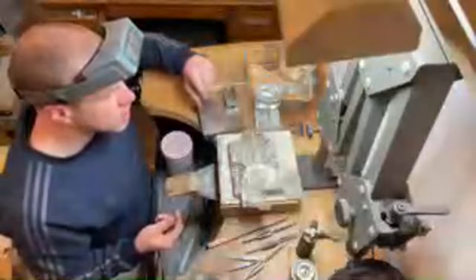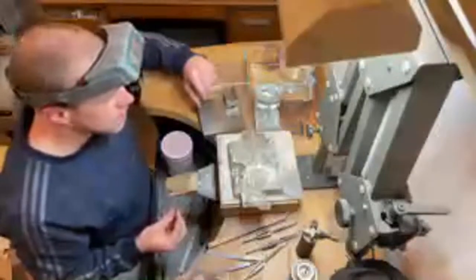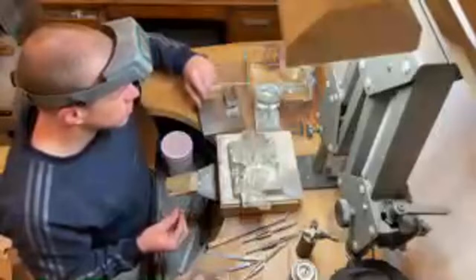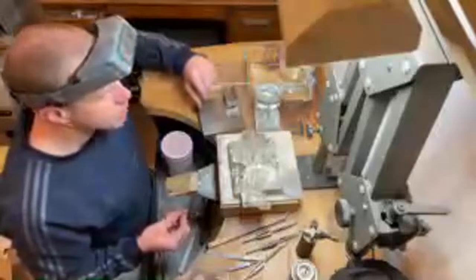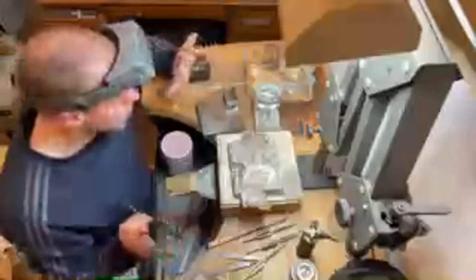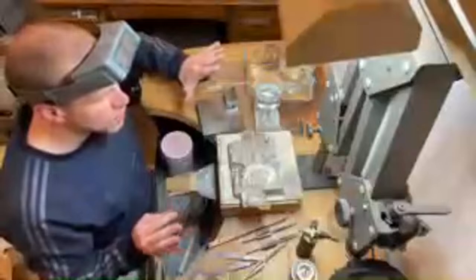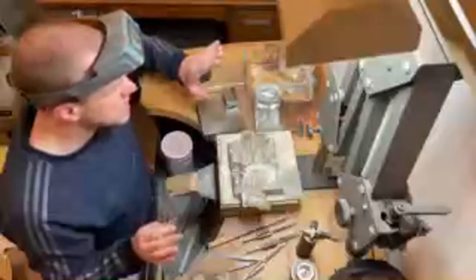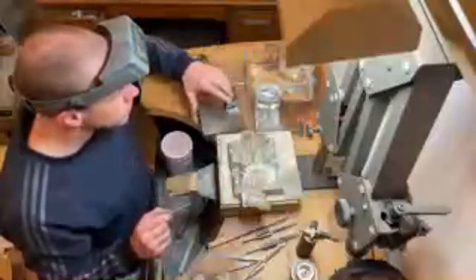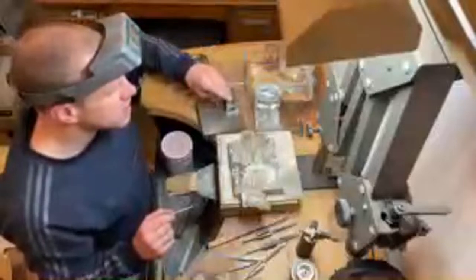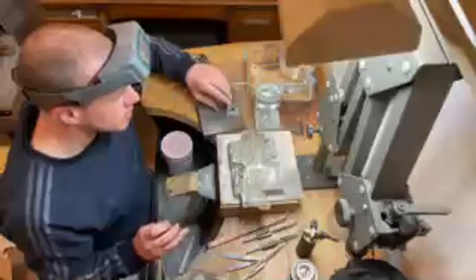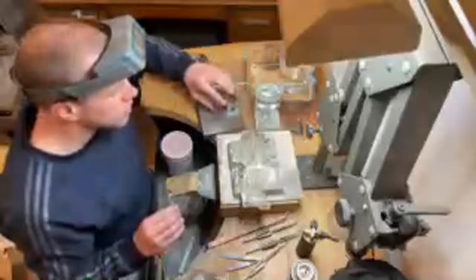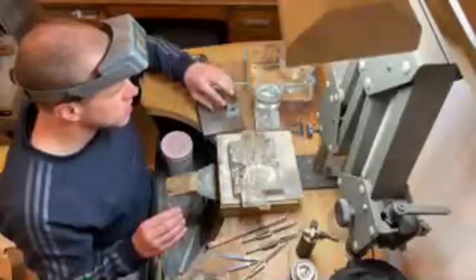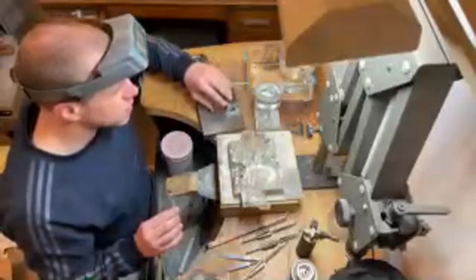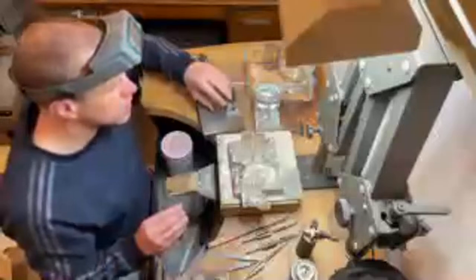I don't know whether it's doing anything actually, because I was having problems. If you quench sterling silver ingots, it's problematic, or it was for us. When you then go to roll them out through the rolling mills, they're like wringing out a sponge. You get water coming out. The silver takes on board whatever you quench it in, which isn't a problem if you don't do any process, like if you do it after soldering, which I did for years, no problem. But when you come to squeeze it, either rolling or drawing, with ingots, it results in blistering. The liquid ends up in subsurface porosity. It expands, you get blistering, which turns into cracks.